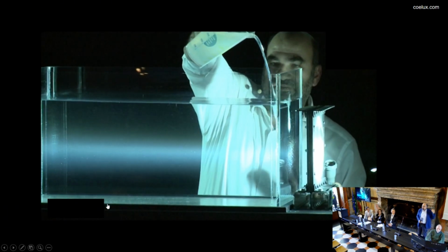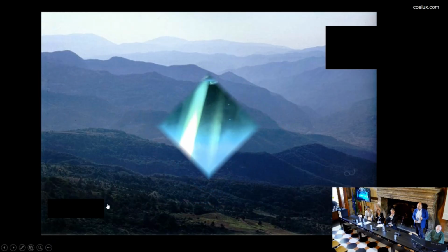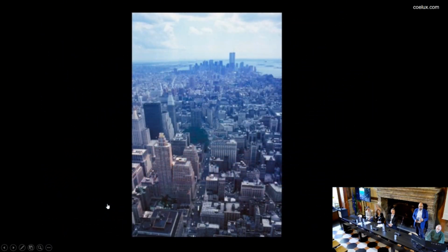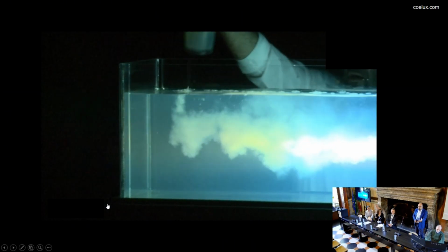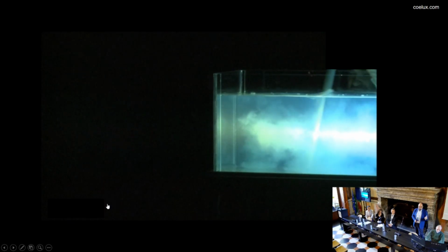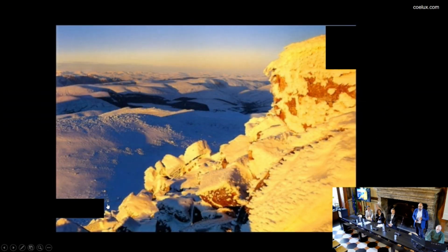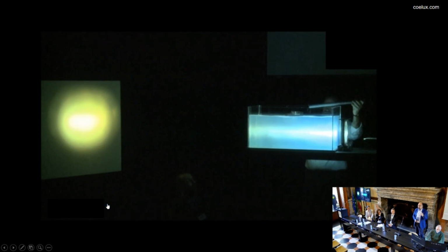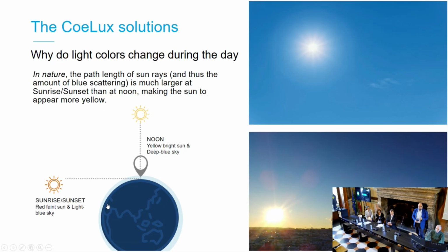But if you disperse fluctuations in density in the medium, like dispersing glass nanoparticles in water, you will see that suddenly the high frequency components of the light get diffused, as with air molecule fluctuations in the atmosphere, and the complementary component, which is yellow, gets transmitted and eventually shines. So these two components, diffused and transmitted light, make the properties of our diffuser, the sky, which is a dichroic diffuser.